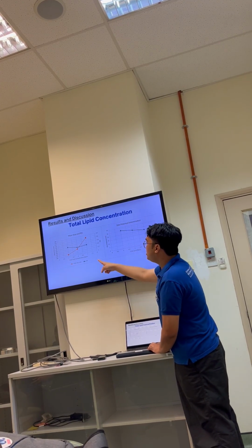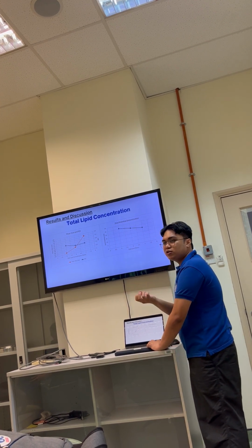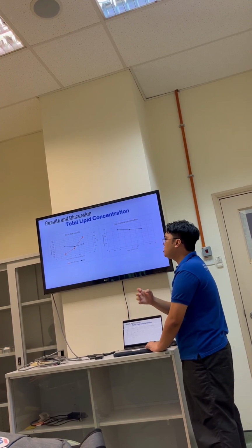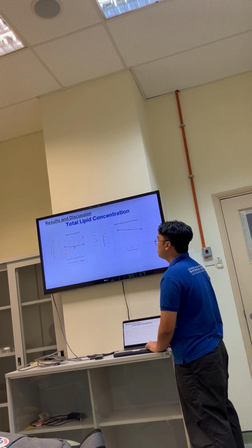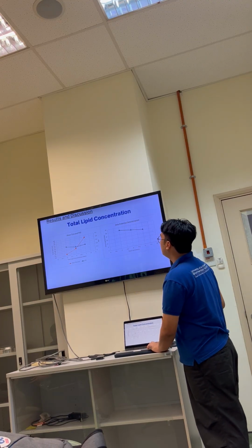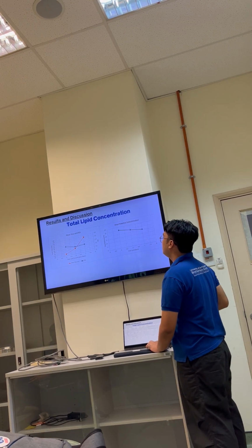Next, the total lipid concentration seems to also show that increasing the said component would also increase the mean size. This is likely because we have a more viscous melt, and because of a more viscous melt during the sonication process, we can get larger particles. So this one is not ideal compared to the 5% one. However, the zeta potential is quite fair, has at least 20 millivolts.